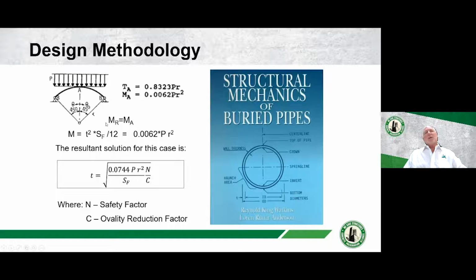So when you combine those and make the resisting moment equal to the applied moment, then you'll end up with this configuration here. You reduce that back to determine what you're trying to calculate, which is the thickness of the liner, and you come up with this design equation. The key pieces of this design equation is that the thickness is proportional to the load that's on there. It's proportional to the size of the culvert. So the larger the load, the larger the size of the culvert, the thicker it needs to be. But it's reduced by the flexural strength of the material. So the higher the flexural strength of the material, the thinner the liner can be to give you that regular structural capacity.